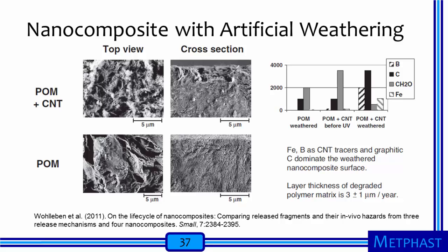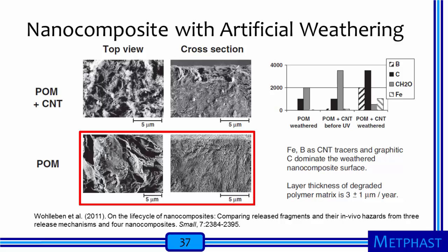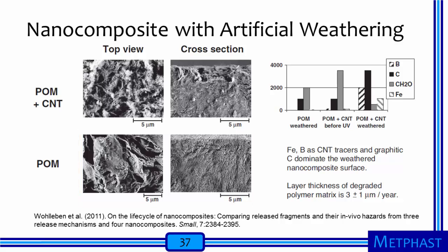As shown in the top view and cross-section images, the surface of the nanocomposite is damaged more by the artificial weathering than the surface of the plain resin, suggesting that the presence of the carbon nanotubes makes the aging process more rapid. The chemical analyses of exposed surfaces in the chart illustrate that the plain POM resin and the POM plus nanotube nanocomposite before artificial weathering have surfaces composed primarily of the polymer. However, the nanocomposite after artificial weathering shows a predominance of nanotubes as evidenced by the presence of significant levels of boron and iron, which serve as markers for carbon nanotubes because they are used during synthesis of the nanotubes to